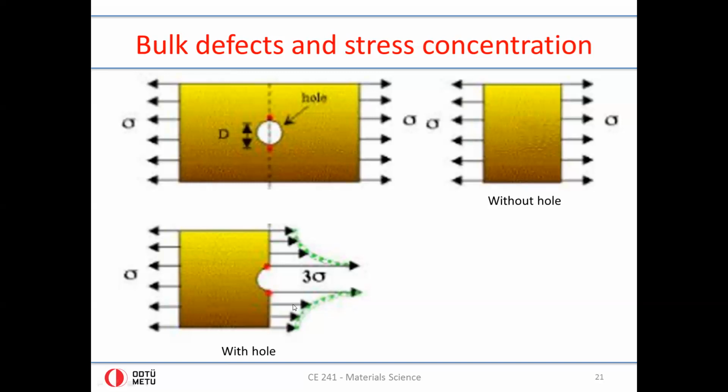And what is observed, and this is calculable, but of course it's kind of early in your coursework for that, is that the amount of pressure applied at the points shown in red, this point and this point, happens to be 3 times the value of pressure applied on average on this side.